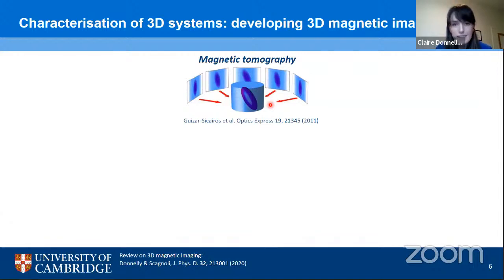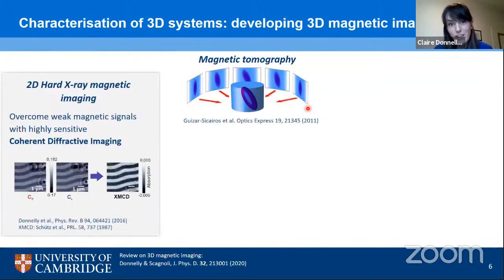Now, when we want to go to magnetic tomography, there are a number of basic ingredients that we need. First of all, we need the 2D projections. And as we're working in the hard X-ray regime now to look at our thicker samples, we actually have to overcome some very weak magnetic signals. So the signal that we're probing is the X-ray magnetic circular dichroism. In the hard X-ray regime, it is much weaker than with lower energy X-rays. In order to overcome these weak signals, we turn to highly sensitive techniques known as coherent diffractive imaging techniques, such as ptychography, and use these to probe these weak magnetic signals with high spatial resolution.